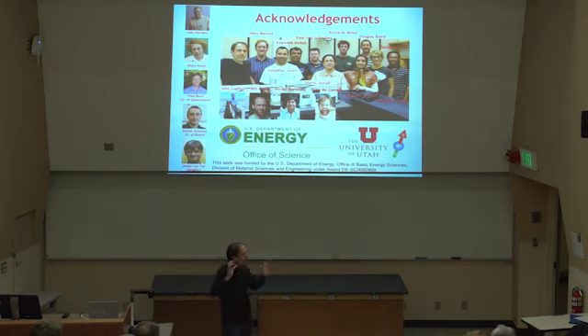at the latest when I showed you this plot about our not quite 5 orders, but more than 4 orders of magnitude in magnetic field and frequencies that we cover, that you actually do not just have one setup. Everyone who's familiar with commercial EPR spectroscopy knows you spend about $1 million and then you get some big machine, and that has exactly not one frequency, but a range of 9.3 gigahertz to 9.7 gigahertz or so. That would be X-band.